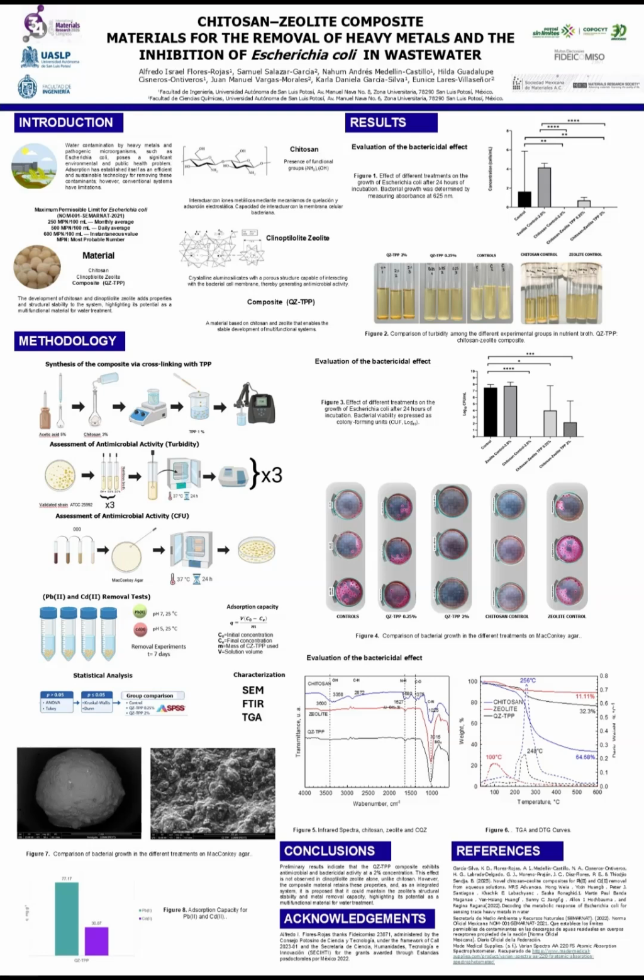Characterization. Microscopic images of the composite reveal an irregular and rough surface, attributed to the incorporation of zeolite into the polymer matrix. The ratio used facilitated the encapsulation of the zeolite structure, leading to the formation of the composite. In the infrared spectrum of chitosan, the functional groups characteristic of this biopolymer are observed: hydroxyl at 3,358, carbon-hydrogen bonds at 2872, amino at 1580 cm⁻¹, and ethers at 1025.